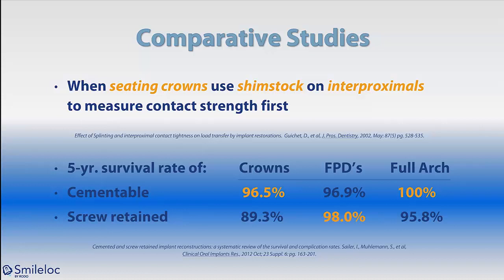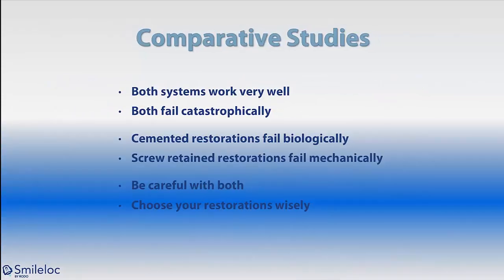With the 5-year survival rate study done by Sailer, we see that cementable crowns have a greater survival rate than screw-retained. We saw that fixed partial dentures, though, are better with screw-retained. And with full arch over a 5-year survival rate, cementable has the greater longevity. So what can we say? Both systems work very, very well, but they both fail catastrophically. Cemented restorations fail biologically. Screw-retained restorations fail mechanically. Be careful with both. Choose your restorations wisely.